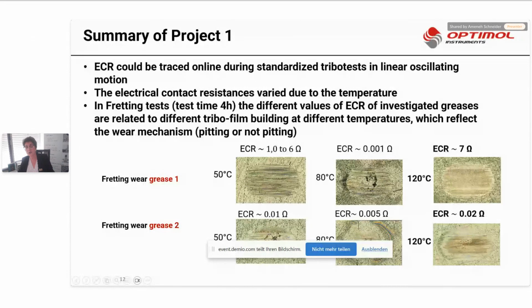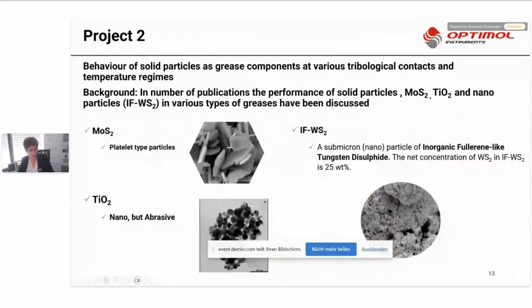As you can see summarized here, grease number 1 at 50 degrees has a moderate electrical contact resistance, good. At 80 degrees, very bad, very low electrical contact resistance, and the best one is 120 degrees with higher electrical contact resistance. And for grease number 2, we had no fretting protection at all at the 3 temperatures.